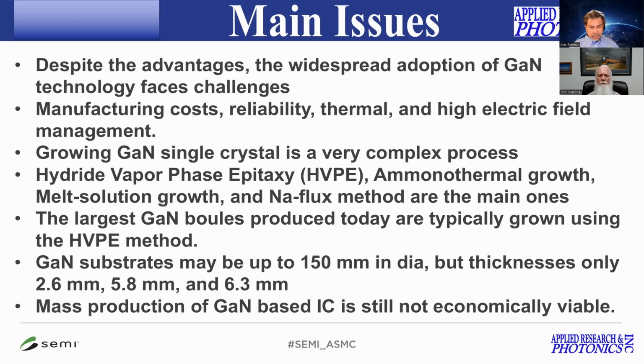So they cannot grow a much bigger boule, although there are many techniques, like hydride vapor phase epitaxy, which is the most commonly used technique. Ammonothermal growth is another one, then melt solution growth and the sodium flux method. These are all effective, but with a silicon boule, you can grow 3 meters long. So in one run, you can get 3,000 or 5,000 wafers, depending on thickness. That's not the case for gallium nitride.